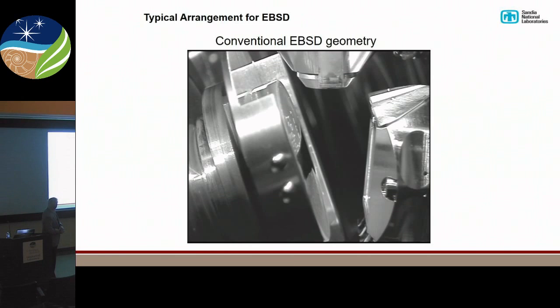So in the microscope, this is what it looks like. And I always tell people there's two kinds of people in this world, those who've hit something inside their microscope with this setup and those who haven't, or those who will. Here's our pole piece for our SEM, so our electron beam comes out of here. It strikes our sample, which is sitting here, and over here is our fluorescent screen. So our diffraction patterns appear over here. We then have a camera mechanism to image those. Down here we have some forward-scattered diodes that pick up the forward-scattered beam. The contrast we see in those is sensitive to the crystallography of the sample. So we begin to see the crystallography, channeling contrast, all sorts of interesting details on those detectors. You can see there's not a lot of room in here. Whoops, there's that button.